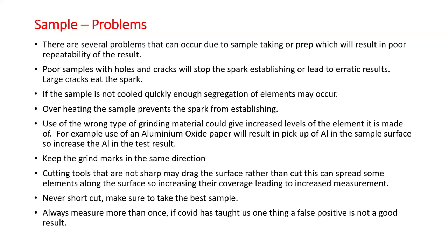I recently re-educated myself with this one, looking at titanium for a customer. It was sparking pure titanium samples, so it should have been CP, commercially pure, and aluminium should have been less than 0.3. And the results were coming out around about 0.5. Measured it on a norm sample. The norm sample came back okay. Measured a couple more samples, exactly the same.